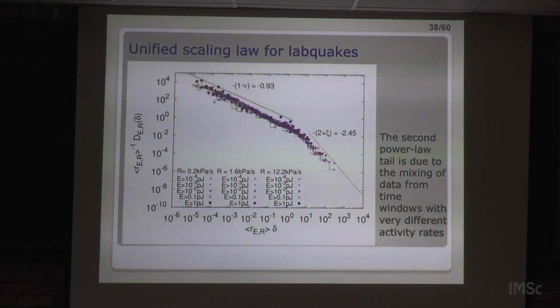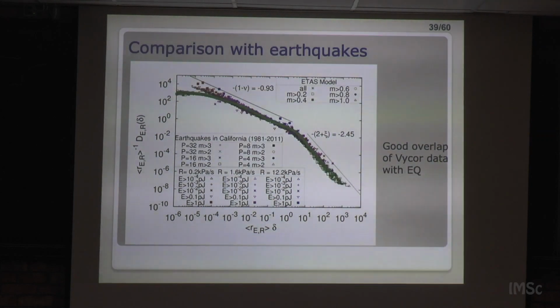And now the unified scaling law, I have already explained it. We get this double power law. These are different, moving the threshold up and down, so we get more sparse or more joint data, and also changing the compression rate. Everything scales very well just by the average, or inverse of the average, waiting time or average rate. And you get these exponents, and on top of this data, you can overlap earthquake data. So this green data is the California catalog, and it overlaps with rather the same exponents here, 1 minus nu and 2.45. So clearly, at this level, the two phenomena are described with identical laws, okay?